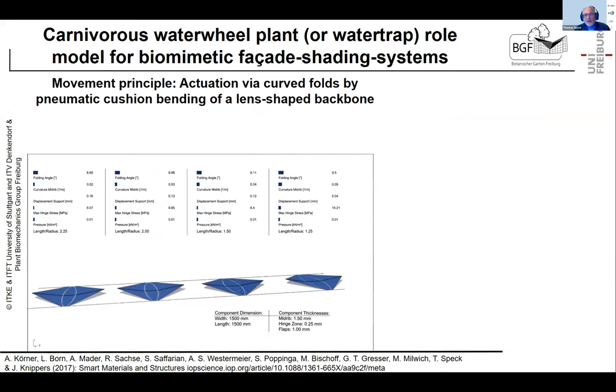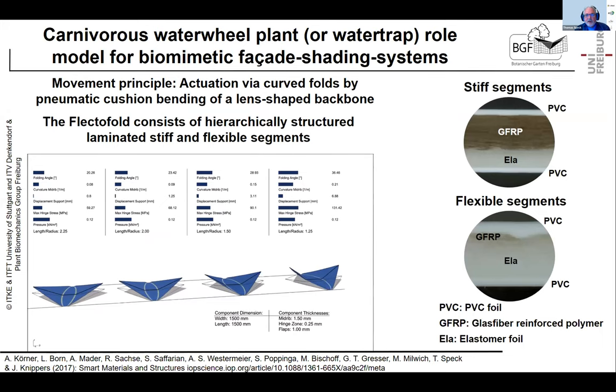These flectofold elements are simply made with a thing which is called vacuum bag method. They consist of a glass fiber reinforced polymer, an elastomer, and two PVC layers as a kind of outer coating to protect them against UV and also to make them look more nicely. And it can be done in one process. In the stiff parts, these are the wings and the central lens-shaped part, you have a lot of glass fiber reinforced polymer. And in the flexible parts, this is mainly these curved folds, you have nearly only elastomer. It looked pretty nice. It worked pretty nicely.